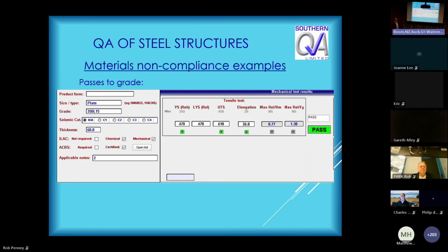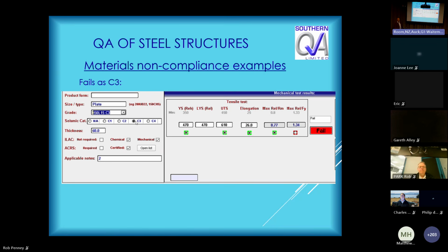Here's an interesting one where the grade, I just mentioned this before, 350 L15 grade, 60 millimetre thick, and you've got to pass. Because L15 has no requirements for Re/Rm and Re/Fy values, for the ratio values of the material to ensure seismic ductility. So it's fine, meets the grade requirements. But hang on a minute. As soon as we tick the C3 box in the database, which says it has to be a maximum of 0.8 Re/Rm and a maximum of 1.33 Re/Fy, suddenly it's got to fail.